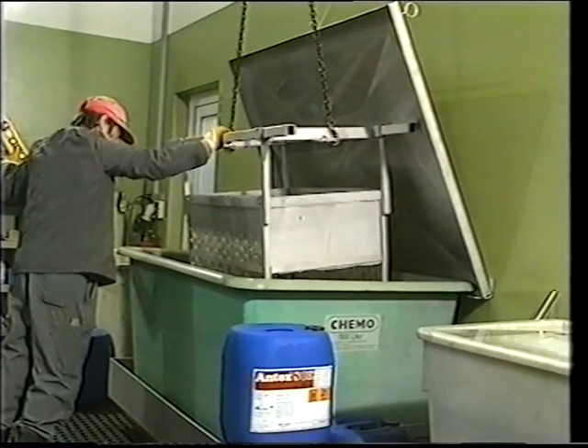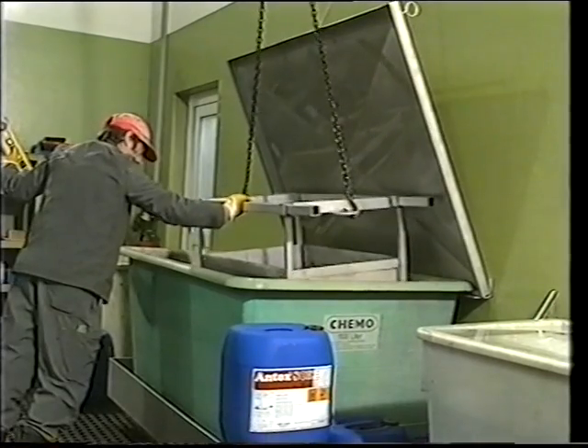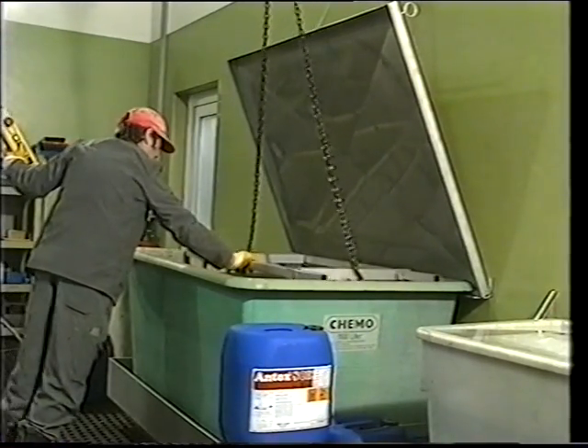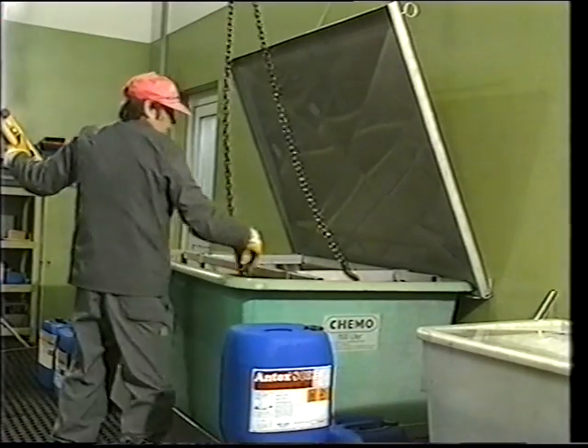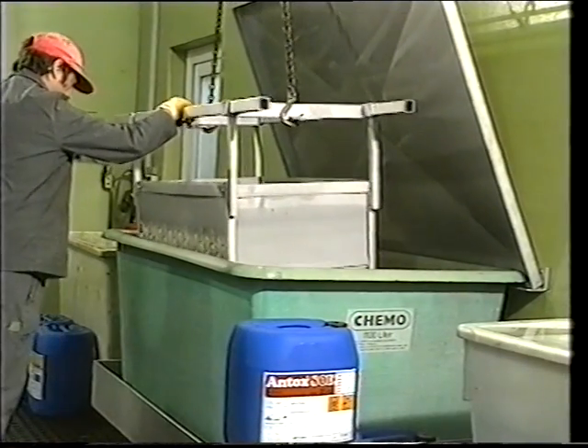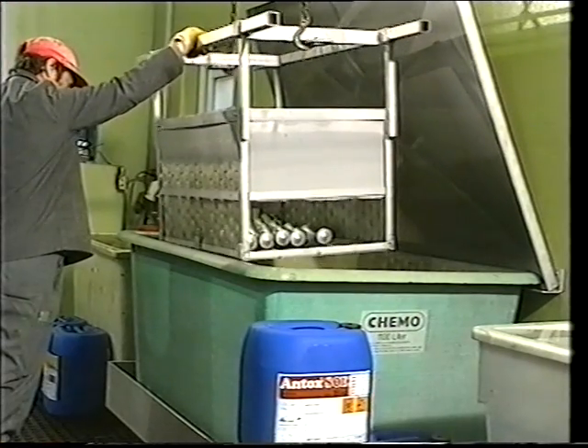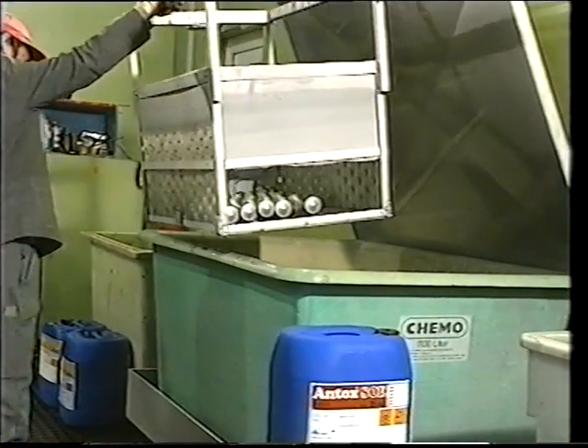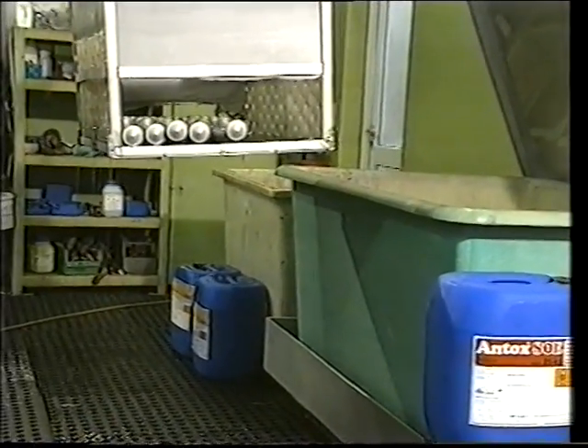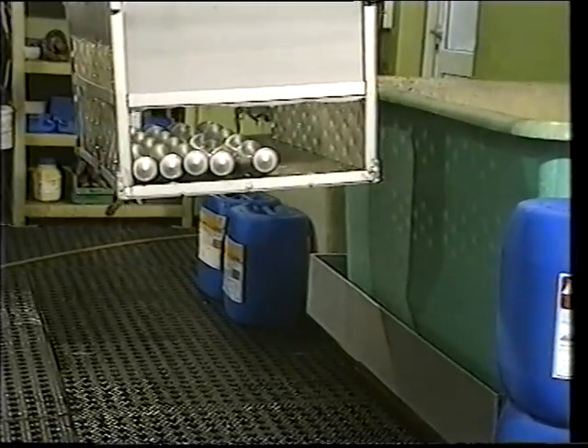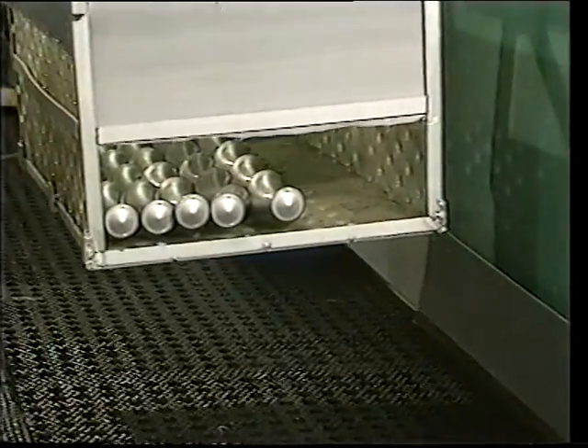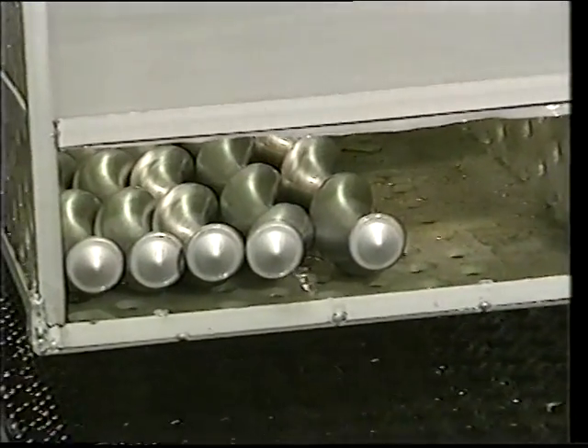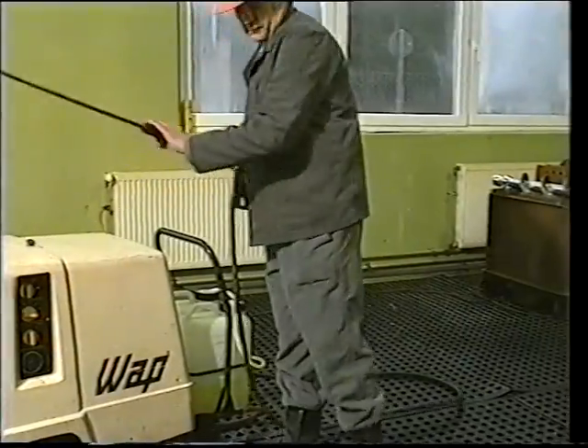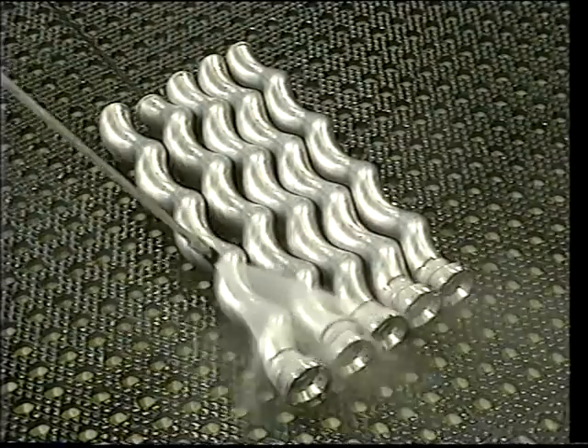The immersion method using Metinox 80E produces completely clean surfaces, thoroughly cleaning not just welds, but also the surrounding metal surfaces and hence providing better corrosion protection. The exact pickling time must be determined by preliminary testing. That time must be strictly observed in order to achieve the desired result. If necessary, Metinox 80E can also be used for more aggressive immersion, for example, to remove stressed surface layers. The amount of material removed depends on immersion time in the bath. Immersion pickling is again followed by high-pressure rinsing.